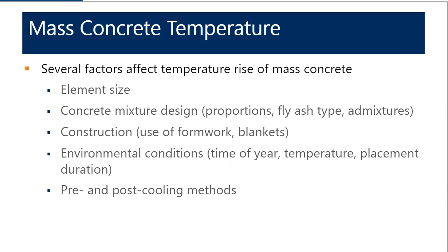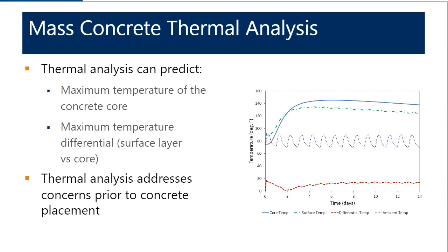And to develop a thermal control plan, it's often useful to perform a thermal analysis that takes into account all of these factors in order to predict what the actual temperatures for the placement are. So here's an example of a mass concrete thermal analysis that I'm showing in the figure on the right. What I'm showing are the predicted core temperature, which is the solid blue line, and surface temperature, which is the dashed green line, and the resulting difference between those, the differential temperature, which is the dashed red line at the bottom. And what this is showing is, for a particular combination of element geometry, concrete mixture, insulating conditions, all of those factors that we just talked about, what are we expecting to be the maximum temperature of the concrete at its core? What are we expecting to be its maximum temperature differential?